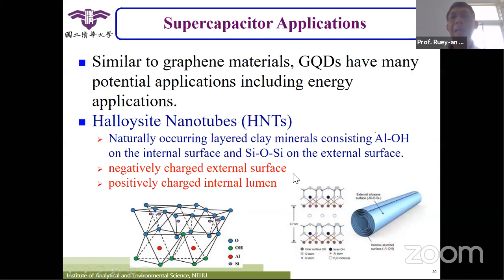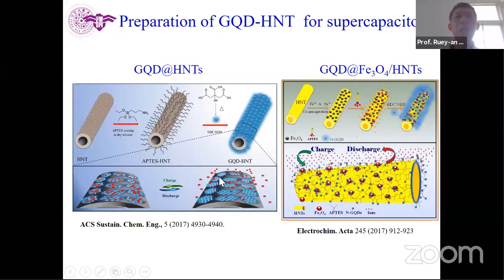So that's quite common. But now we use this for energy application. Since the outside is negatively charged and the inside is positively charged, we can try to let the electrons get inside, so they can store some energy here. And then we put the graphene quantum dots on the surface. So here is the case. When we put the graphene quantum dots on the surface and do the surface modification, we can see this one is the halloysite nanotube. After the surface modification, we can get good absorption abilities from the GQD.